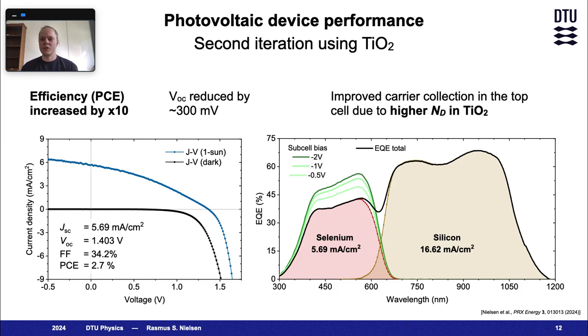Another advantage of using TiO2 is that it is much easier to dope highly N-type, which allowed us to increase the depletion region width in selenium substantially. The consequence is a significant improvement in the carrier collection efficiency, as you can see from the EQE.